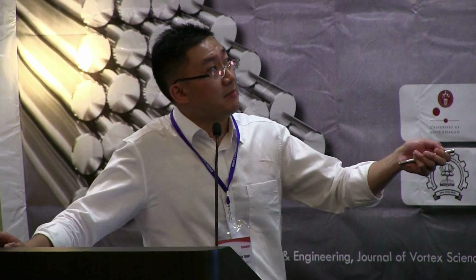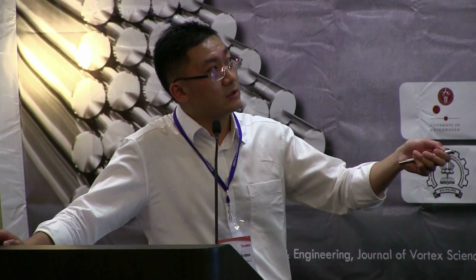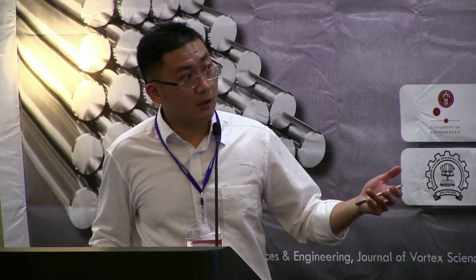So how can we do this? We use the modified Hummers method, where we make the graphene oxide. This is graphene oxide with a lot of functional groups here. And we go through the hydrothermal process. The electrostatic attraction will stack the individual graphene sheets into a three-dimensional structure. So we can obtain a hydrogel, which mostly consists of water and graphene oxide, reduced graphene oxide. After you freeze-dry at minus 80 degrees Celsius, you can get a well-structured porous graphene aerogel.